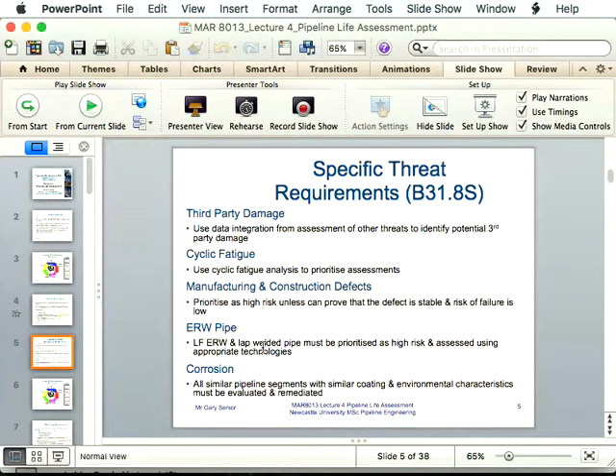So you'll typically get a stress concentration, maybe 2 or 3, at the weld. So if you have a cyclic stress in the base metal of say 100 newtons per millimeter squared, you could be at 200 locally at the weld toe. So it's just going to grow the defect a lot quicker, or plastic collapse it, I suppose. It is overmatched. It could be, yeah, and also bearing in mind you've got increased hardness there,